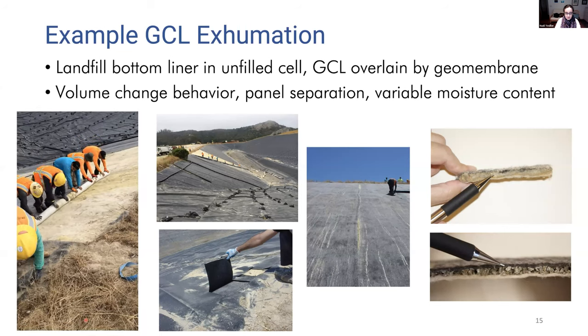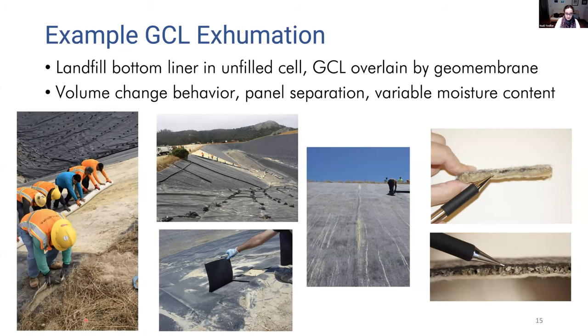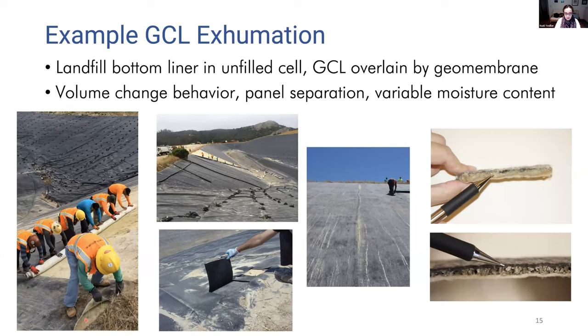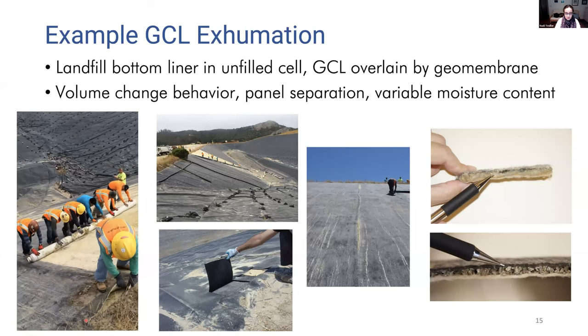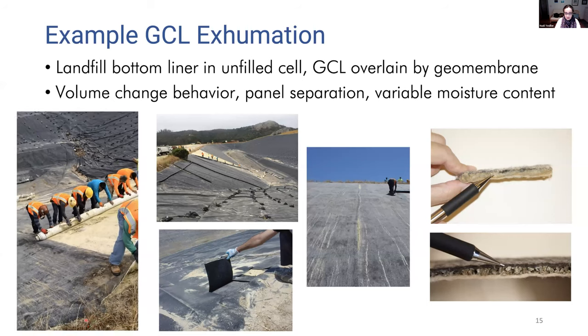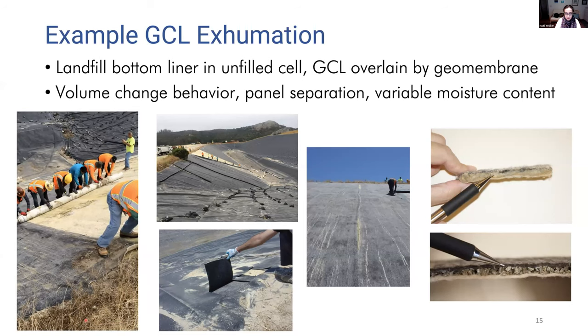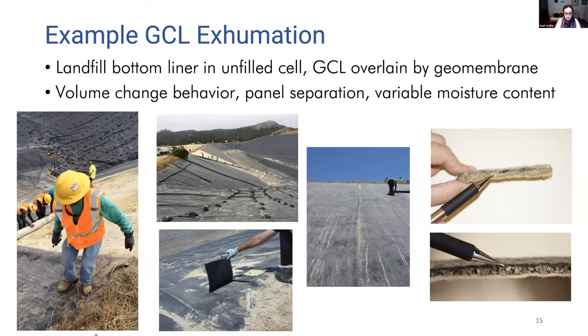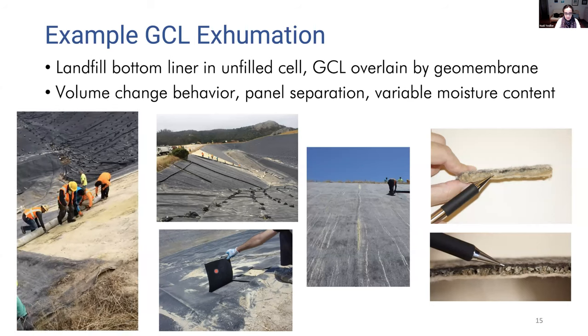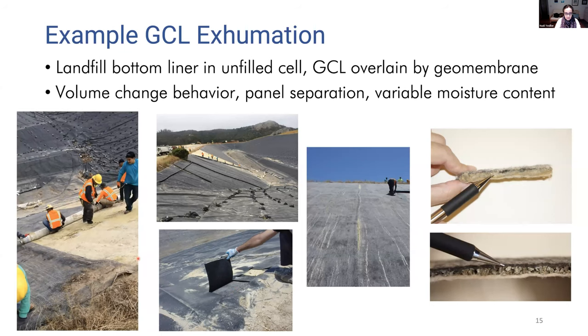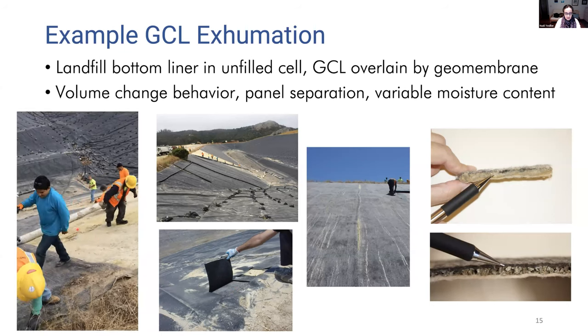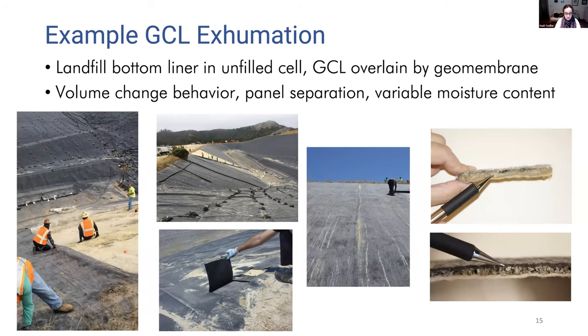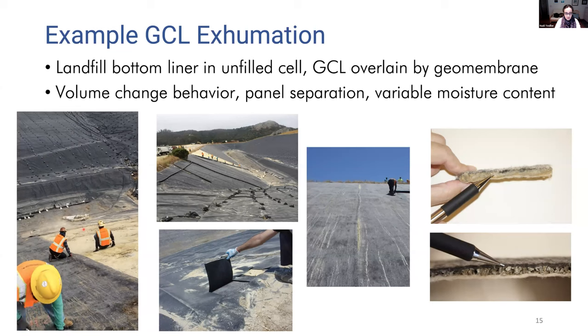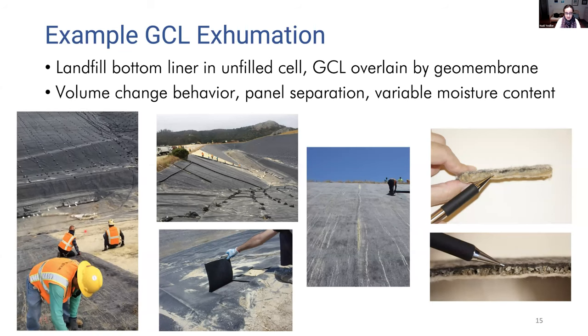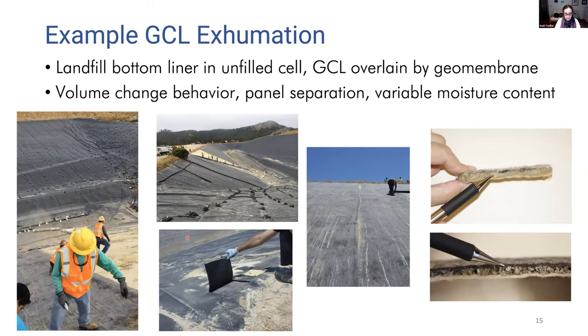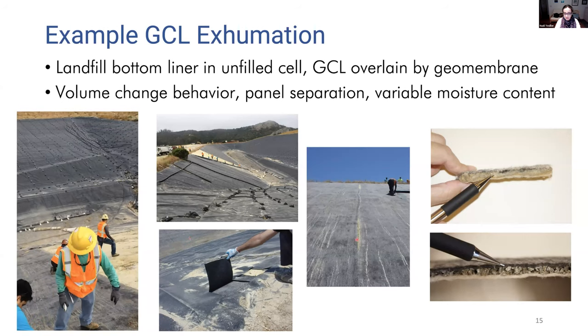The liner was exhumed for replacement with a new set of materials. We had an opportunity to observe the exhumation process and also collected samples from the field for determination of different properties of the materials. We collected samples from both the geomembrane and the underlying GCL material. We observed that the moisture content of the underlying material was variable, very dry near the top, somewhat more moist near the bottom. The GCL also was highly variable depending on the location of the samples that we collected.